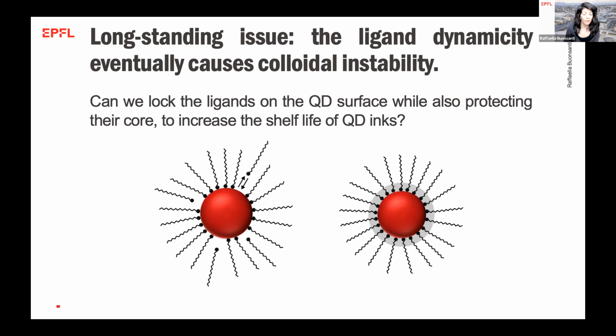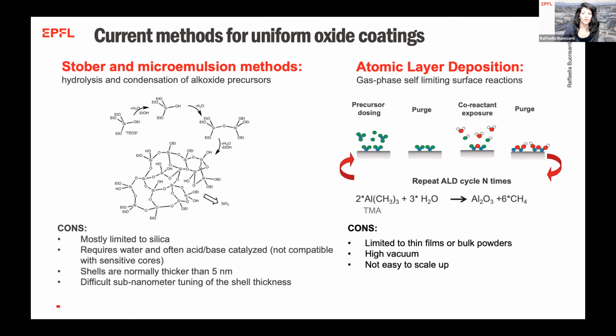So we thought if we could actually build a thin shell around these nanocrystals. We wanted to build a thin shell of oxides similar to what happens in atomic layer deposition. Now, to build this thin layer of oxide, in the past, there are silica coatings that have also been widely used for biological applications. But these silica coatings generally are synthesized by Stöber or microemulsion methods that require water and often acid or base catalysis, and this is not compatible with the sensitive cores. Also, we have quite thick shells, so they don't work if, for example, we would still like to have some charge transfer happening, and it's difficult to fine-tune the shell.